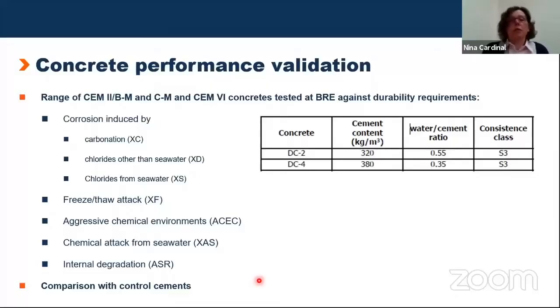This program consisted of a range of concretes being made with CEM2 BM and CM, and also the new CEM6 cements. The concretes were made to the DC2 and DC4 class, with the increasing cement content here and the associated reduced water to cement ratio for the DC4 class. And an extensive test program was carried out by the Building Research Establishment, which looked at the durability requirements for corrosion induced by carbonation and by chlorides from seawater and other than seawater. Also the attack from freeze thaw and aggressive chemical environments, as well as from seawater, and the internal degradation, the alkali silica reaction. The concretes with the new cements were compared with concrete made with control cements.